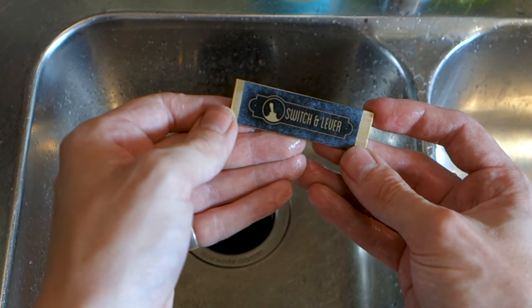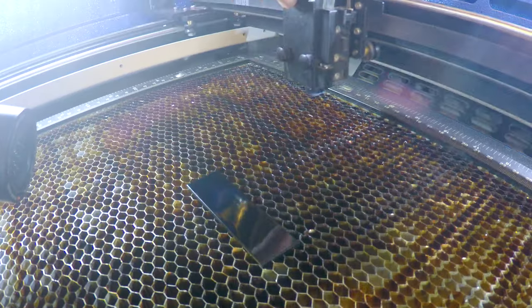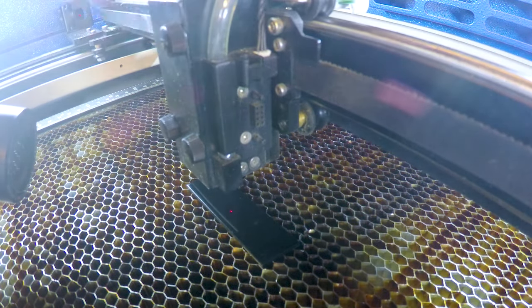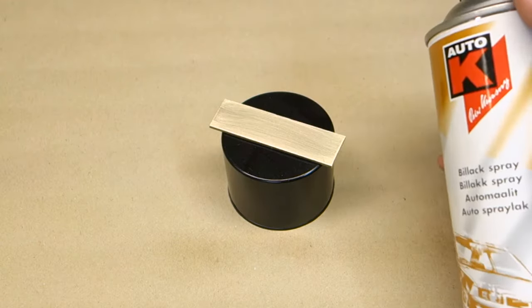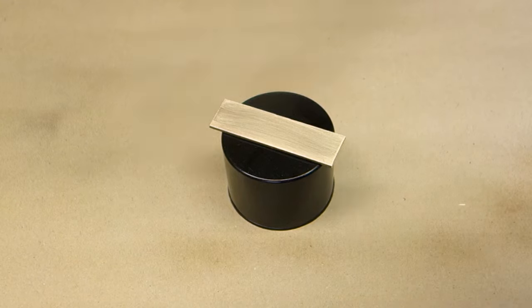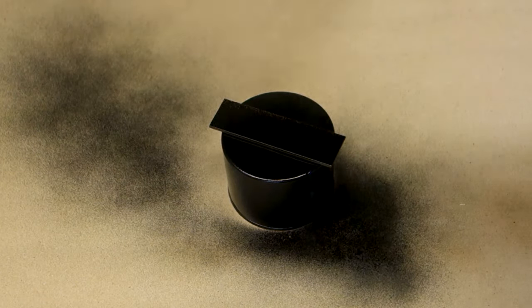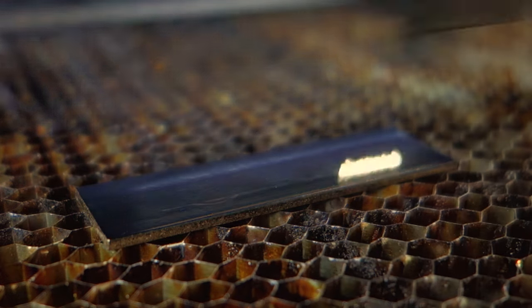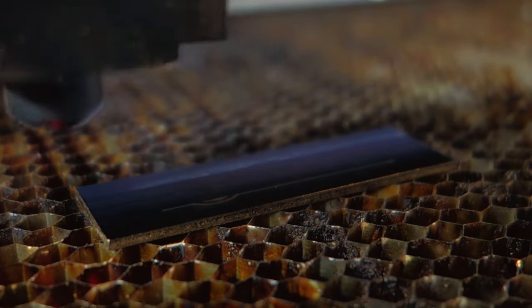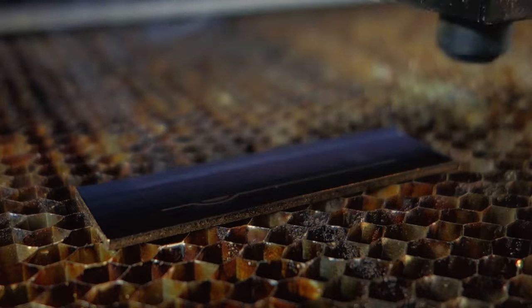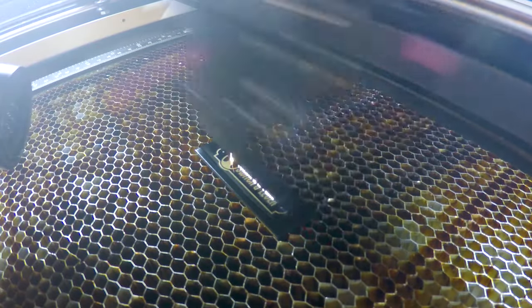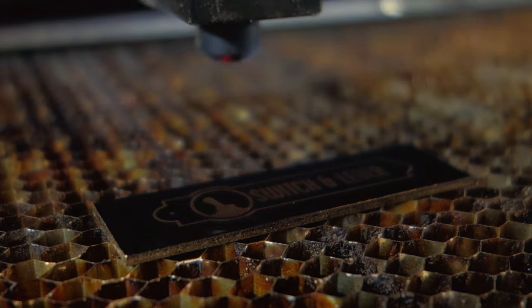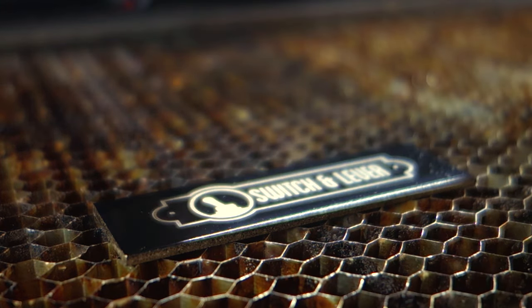The second method is even a bit easier, but it does require some specialized machinery. Take your prepared brass as before and simply paint a couple of layers of regular black spray paint on top. Once dry, lay it into a laser cutter and etch away the paint from the brass in the design of your plaque. The laser won't affect the brass at all, we're only removing the paint in this step to create something similar to the result from the last method.